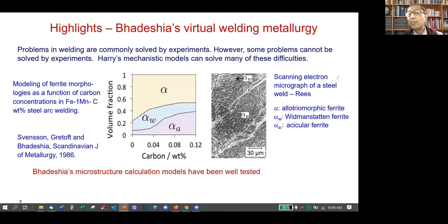And one of Harry's models that we have used is his welding microstructure prediction models for carbon steels and low alloy steels. It allows you to model ferrite morphologies and volume fractions, and this particular plot I have taken from one of Harry's older papers, 1986 Scandinavian Journal of Metallurgy, with Professor Bhadeshia and Gretoft. And this model has been used widely by many researchers. Several of my students have benefited from this work, and it predicts the volume fractions of grain boundary ferrite, Widmanstatten ferrite, and acicular ferrite, which can then be tested by doing experiments. So that was part of Harry's talk in 2004, the Adams lecture at the American Welding Society.